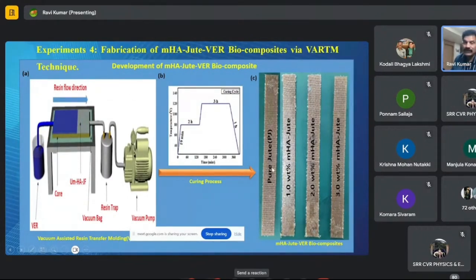Before, this is the pure jute without any addition of flame retardant material. After addition of flame retardant material, you can find the flame retardant material on the surface and inside of the material. So this is the panel, a plastic panel. The plastic is vinyl ester resin. So 1 weight percent, 2 weight percent, and 3 weight percent of MHA we have incorporated on the jute, and we used the VARTM method to pass the resin through the jute for the VER composite material.